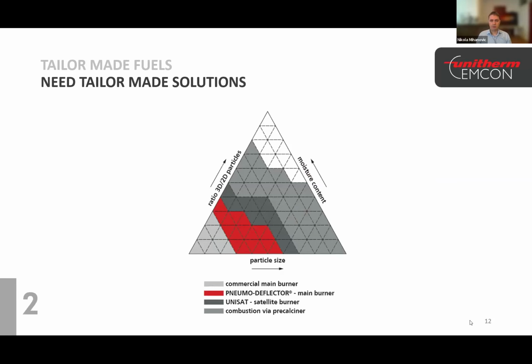There is also the effect of increased kiln inlet temperature, because even very well prepared secondary fuels are not as refined as coal or petcoke, which means that they take longer to combust. This delay in combustion and heat transfer to clinker can result in higher inlet temperatures. It is definitely crucial to have a main burner that provides flexibility to make all the necessary adjustments. And also, we must take into account that we introduce additional moisture from secondary fuel and additional cold air introduced by pneumatic transport, as these factors also increase the specific heat consumption of the system.